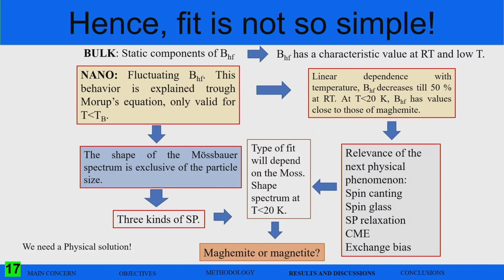Bulk samples easily have static components of the magnetic field. The hyperfine magnetic field has a characteristic value at room temperature and at low temperature as well. And for the nanoparticle, of course, it will depend on many important parameters. I have tried to summarize from my experience and several studies focusing on Mossbauer spectroscopy analysis and other techniques that we have a fluctuating hyperfine magnetic field. This behavior is explained using the Morup equation, as shown yesterday by Gustavo, below the blocking temperature. Of course, the shape of the Mossbauer spectrum depends on the particle size, and the type of the field will depend on the Mossbauer spectrum shape. A temperature smaller than 20 Kelvin is preferable to start to notice a difference between magnetite and maghemite. So we cannot say anything at room temperature. We can try many models, but this is not correct. It's a mathematical solution, but not a physical one.